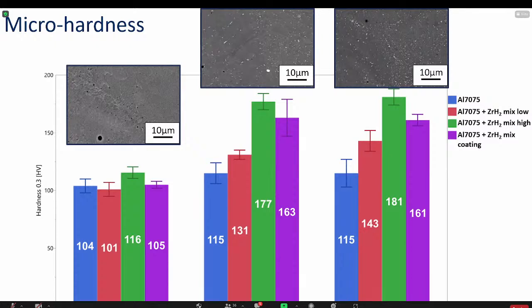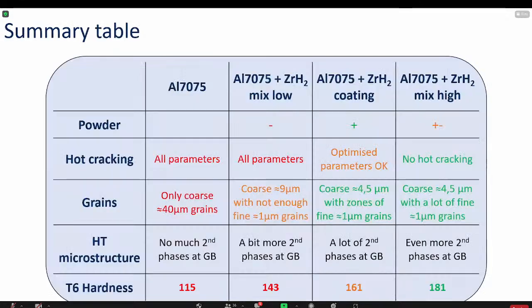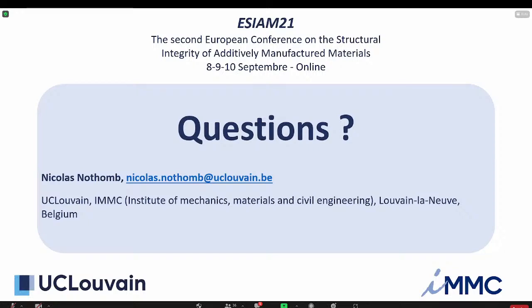So it means that there is still a lot of room for improvement for the heat treatment for the specific LPBF alloy. And so we are currently optimizing this heat treatment to obtain better mechanical properties. And currently we have obtained 181 Vickers hardness. So it's quite good. And we can see that the coated powder also has a lower hardness than the mechanically mixed one, probably because there is a lower amount of smaller grains in the microstructure, like I explained during my presentation. And so I'm just going to stop there for my presentation now, to leave time for questions if there are any.